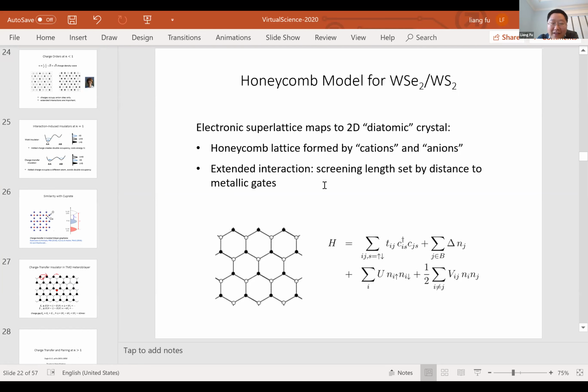I think it may depend on angle weakly, but what it will certainly depend on is pressure. I think pressure will be a very good way of increasing the energy scale in the problem. As you apply pressure, the Moiré potential becomes deeper. When the Moiré potential becomes deeper, you can go to the strong coupling regime at a smaller Moiré period. When the Moiré period decreases, the characteristic interaction energy e squared over L becomes larger. So I think pressure might be a good way of increasing the energy scales in the problem.